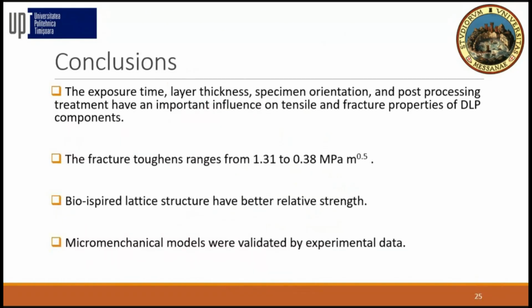So to conclude, there are many parameters which influence the properties of additive manufactured components: exposure time, layer thickness, specimen orientation, post-processing treatment. All have a very high impact on this. Looking at the fracture toughness, this ranges from 1.3 to 0.38 megapascal square root meters, depending on the manufacturing parameters. We observe that the sponge structure, which is a bio-inspired lattice structure, has the best relative strength, and we validated some micromechanical models to describe the Young modulus and tensile strength of these materials.